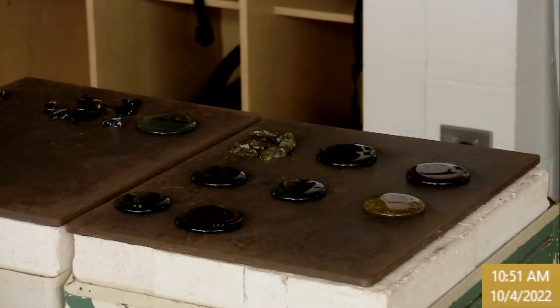The factory's equipment feeds precise amounts of the materials into a furnace. After 24 hours at 1500 degrees Celsius, a gooey liquid that's the consistency of honey is produced. The molten glass pours out of the furnace. Shears cut the flow at precise intervals to produce cylindrical globs. Each glob is the exact amount required to make up one bottle or jar. They drop to a device called the scoop. The scoop moves them to troughs that feed them to jar forming and bottle forming machines.